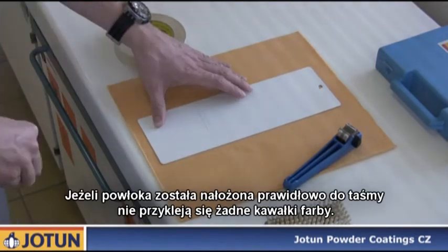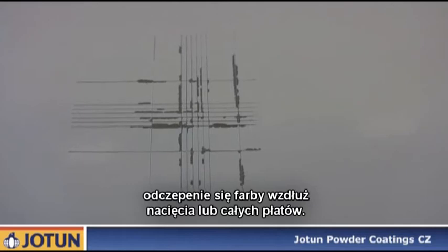If the adhesion of the coating is at an adequate level, the coating will not separate from the substrate. If the coating is not cured properly, you will see a loss of adhesion along the edges of the cuts, or whole squares of the lattice detached.